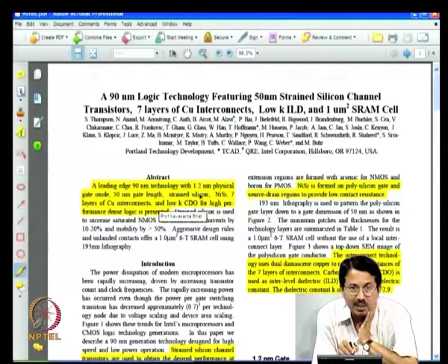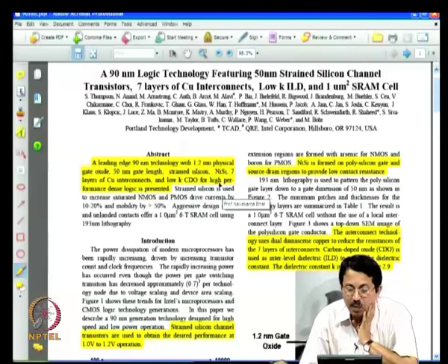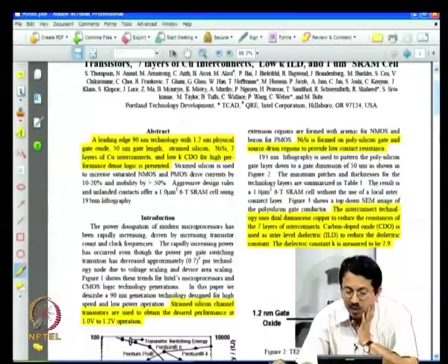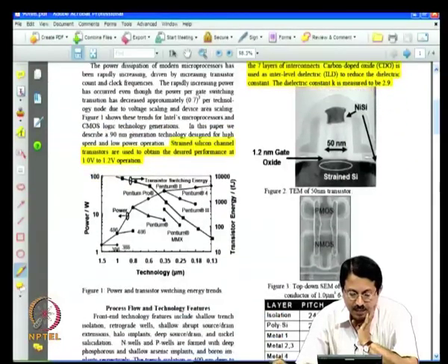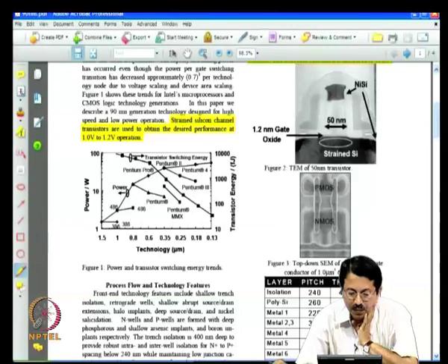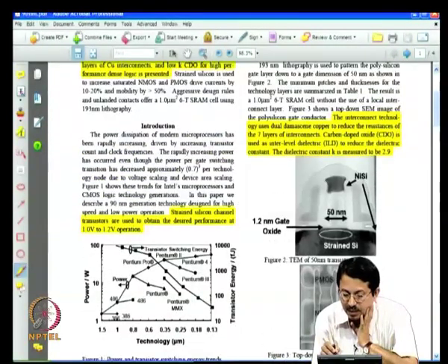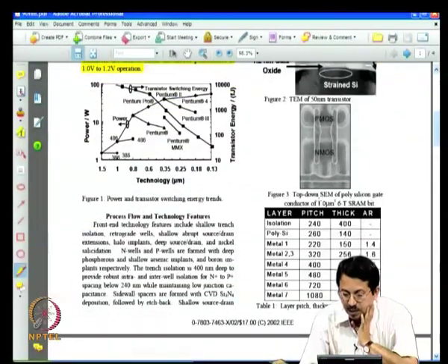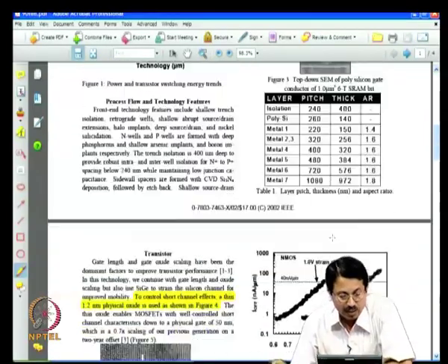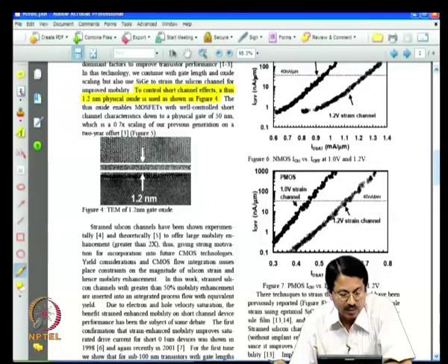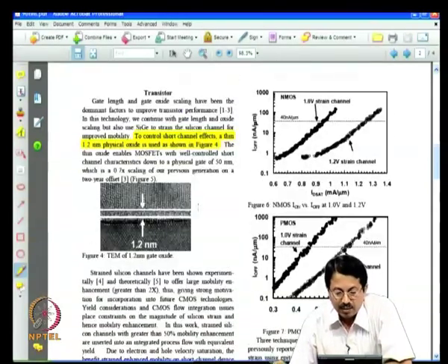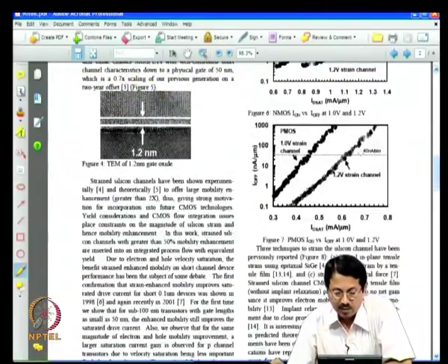This uses 1.2 nanometer oxide. It is even thinner than previous generation, and nickel silicide instead of cobalt silicide. Now there is some more optimization, and this is the cross section of a transistor. Channel is strained silicon, 1.2 nanometer gate oxide, 50 nanometer gate length, nickel silicide is shown here at the source, drain and at the polysilicon. And they have been able to make a 6-T SRAM cell using the technology. This here just shows that you have silicon and 1.2 nanometer oxide and polysilicon gate. Okay, and typical off current versus on current for N and P channel transistors.